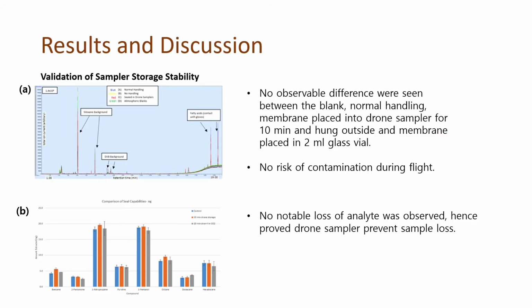Okay, in the figure here, the chromatogram is shown in figure A, and it consists of a known PDMS background and a minor DVB background, and both of them are known to come from the membranes themselves. There was no observable difference between the blank desorption of an unused membrane, one given normal handling, a membrane placed into the drone sampler for 10 minutes and hung outside, and another membrane placed in a 2 ml glass vial for 10 minutes. So it indicates that the samplers were not at risk of being contaminated from the atmosphere when they were placed on the drone for flight.